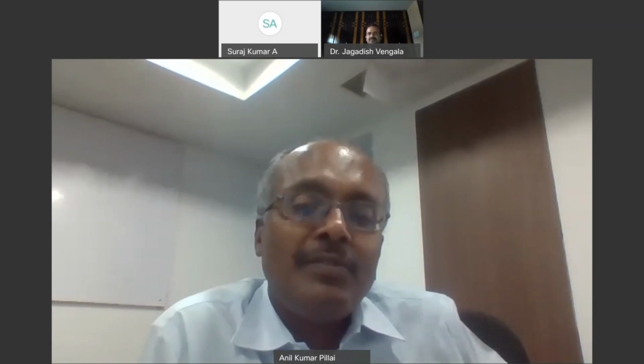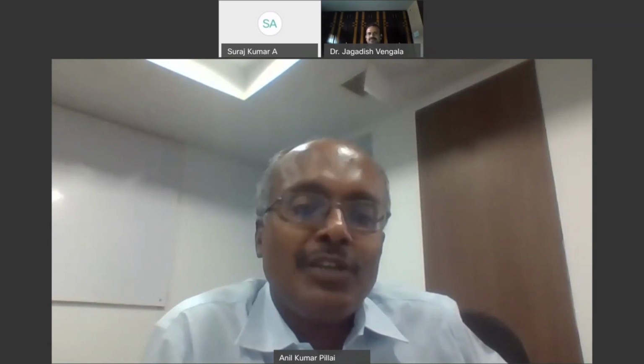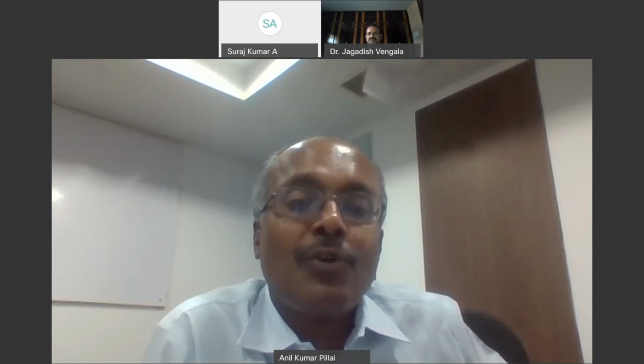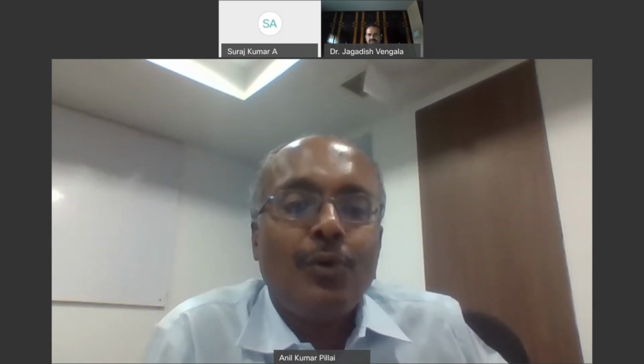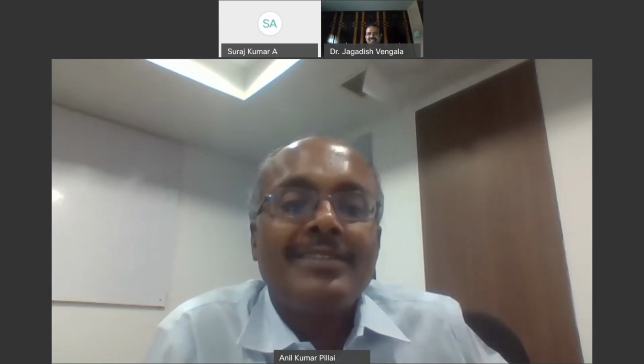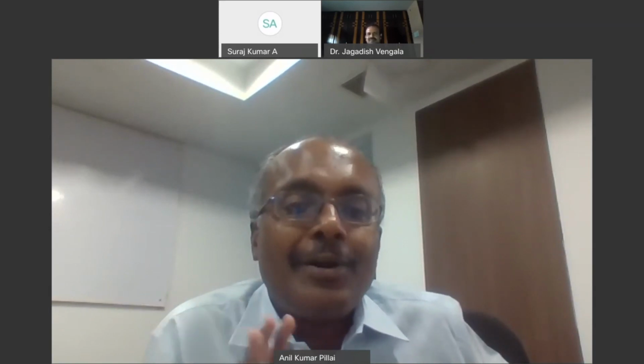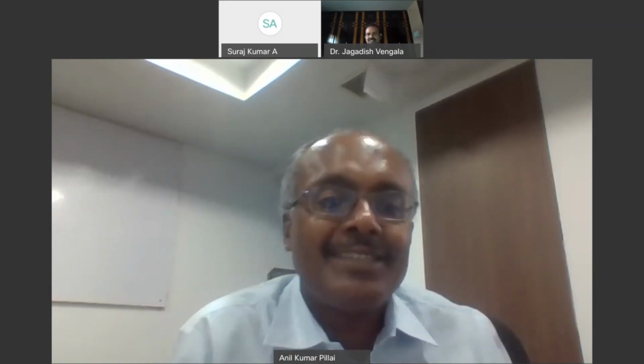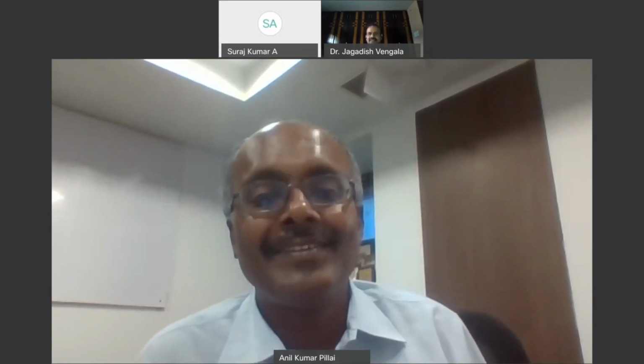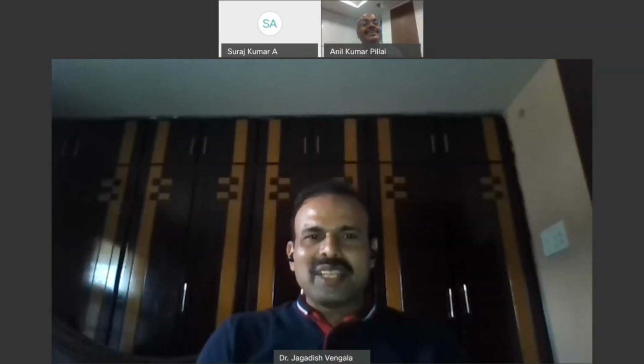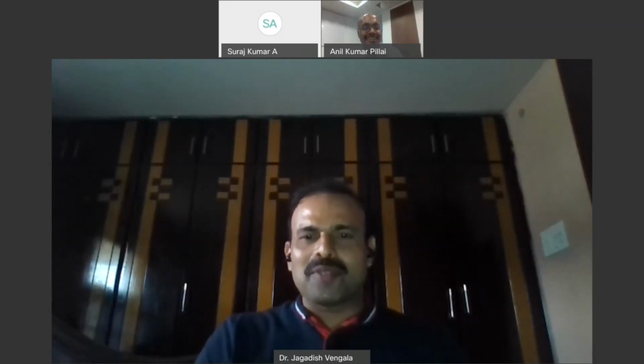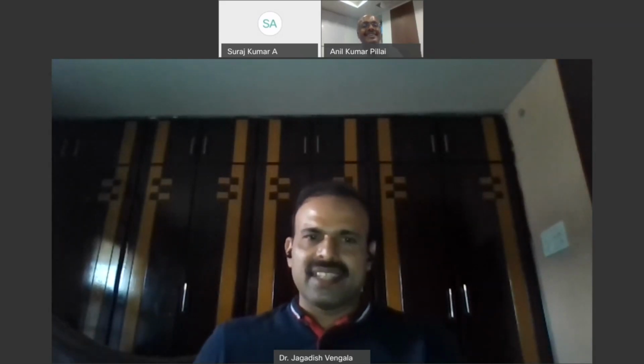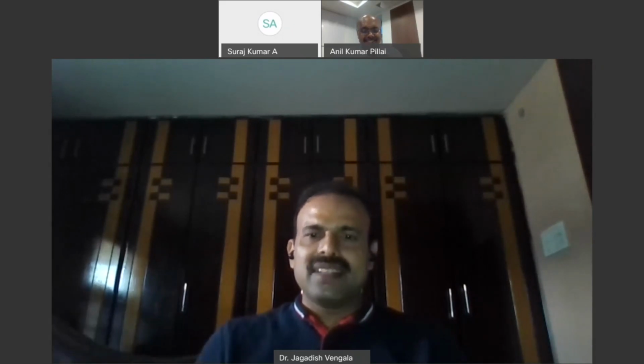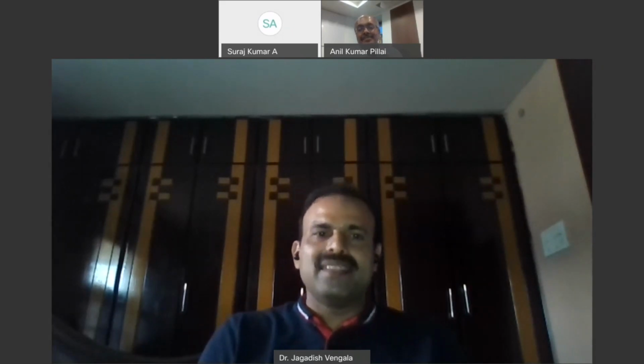And another very important point which you had mentioned in your presentation, and which we have also seen at sites, is that whenever they adopt this volume batching of 1:2:4, and when it is converted to actual weights, we tend to see that sometimes the cement content is more, or they miss the aggregate quantity in practical sites, if nobody is monitoring it. That's why I showed you some case study. If you directly adopt 1:2:4, what happens when you convert into weight, and how the strength varies. So I thought it should be given.